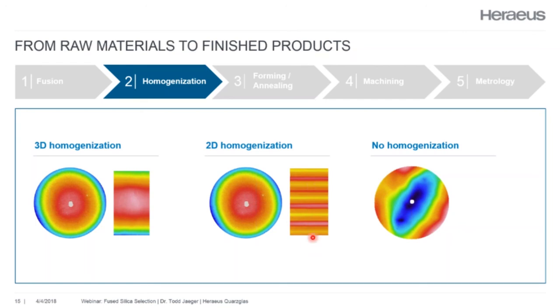So these edges or steps that you're seeing here come from the stacking up of the fused silica layers during the deposition process. If we run the homogenization again in the opposite direction, we can homogenize in that other area that was not homogenized for 2D. And this gives you a material that's excellent for making prisms, retroreflectors, etc. for 3D optics.